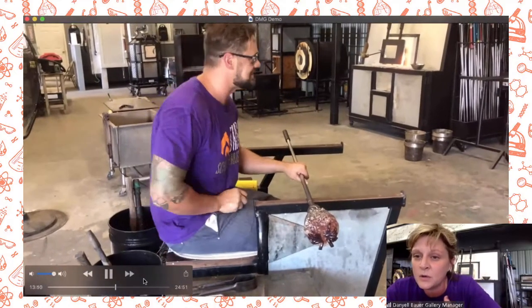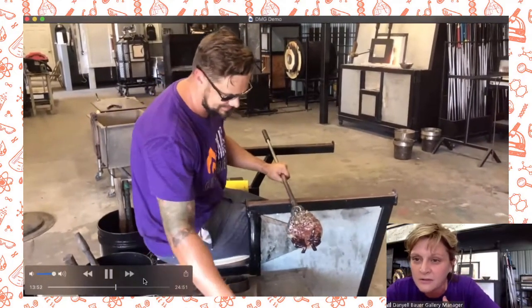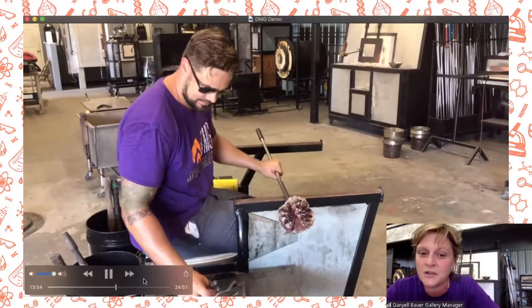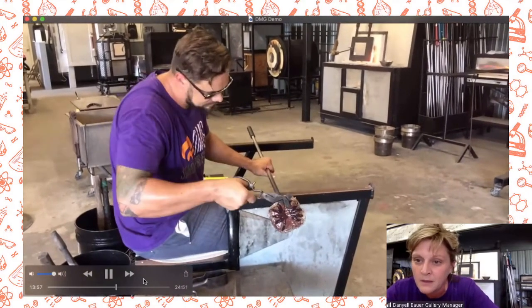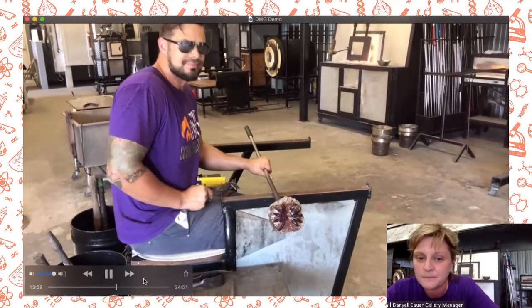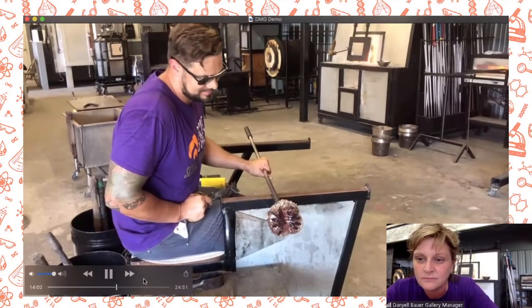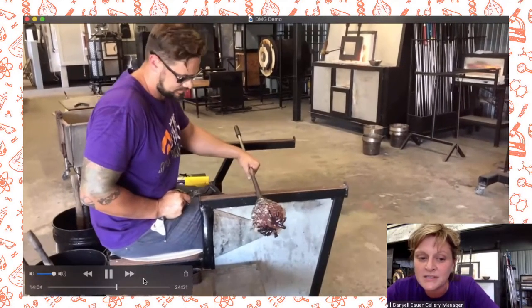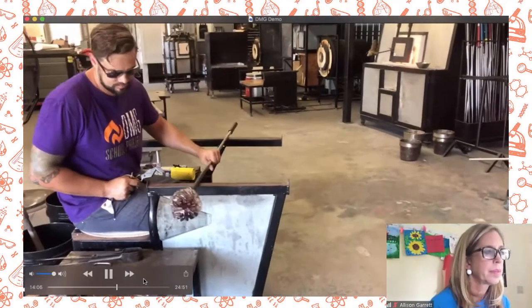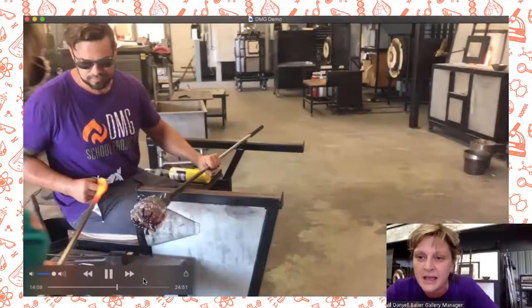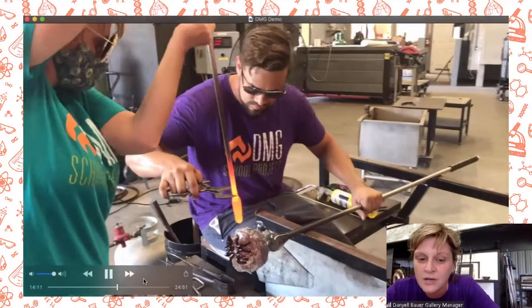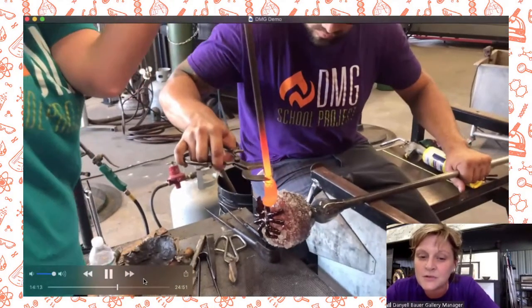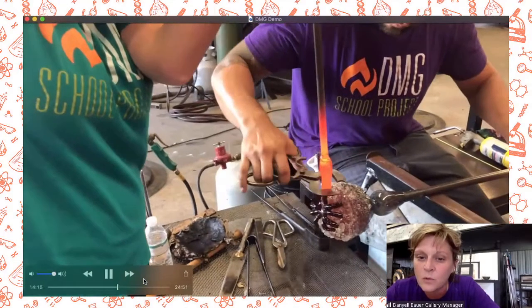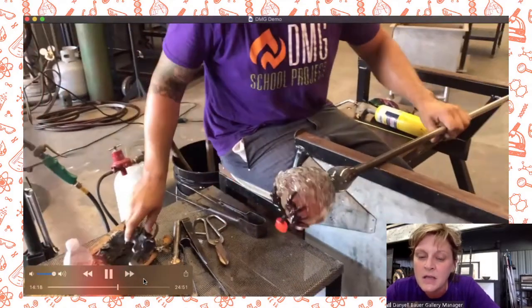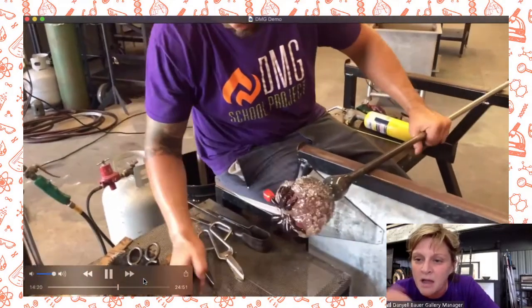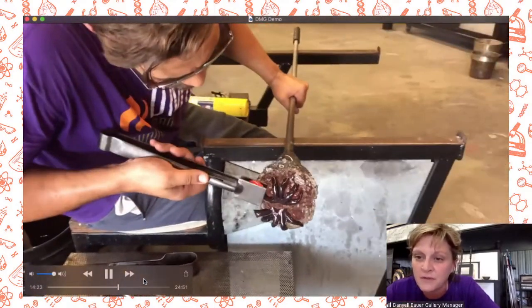And remember, if it gets too cold, it'll go into thermal shock and fall off the pipe. Thermal shock is when the glass cools too quickly and it will just crack. It stresses the glass out. So at the end, when he wants to keep this piece, we have a kiln set up, and that kiln is at 920 degrees because the glass goes into thermal shock at about 900. So we have our kiln set at 920 because it's above thermal shock but under the molten temperature of 1,000.